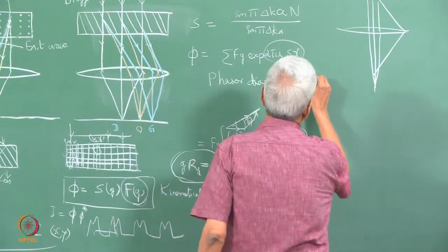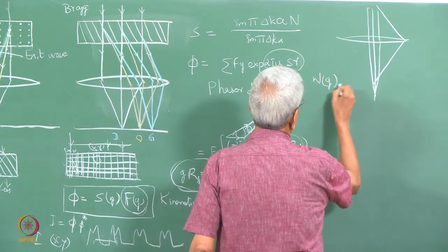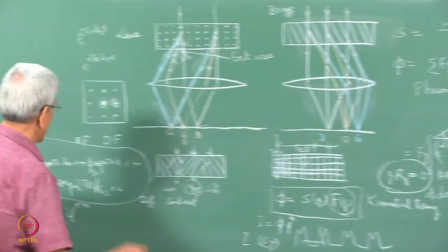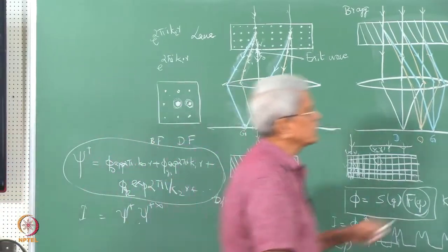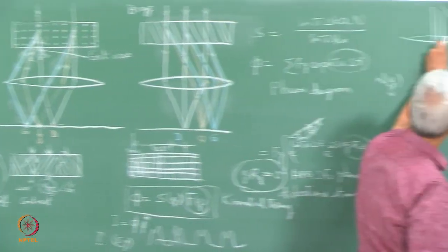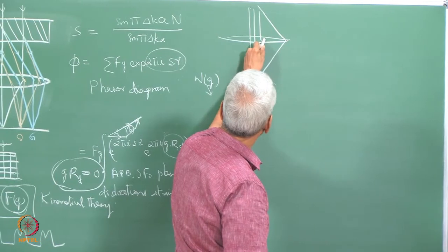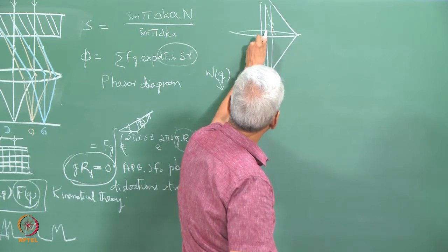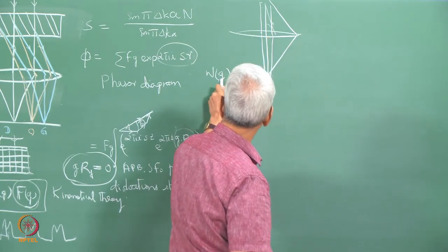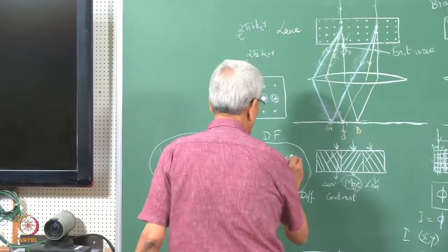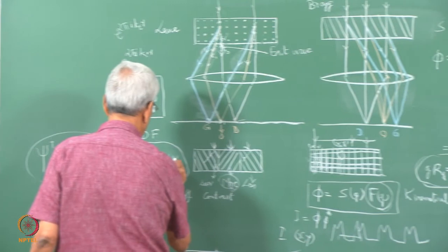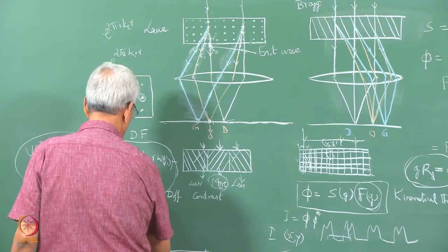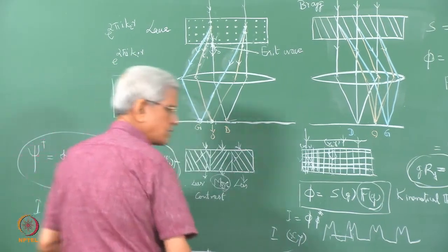This factor is essentially a phase factor, which we normally denote by a term Wg. This factor will be added to all the terms, and it is not going to be the same. It depends upon the angle which the scattered beam makes with respect to the optic axis, or the distance from which it reaches the lens. Depending upon that, this value will change. So, in these cases there is another factor phi g1 plus here, and another factor g2. This will be added to the various terms.